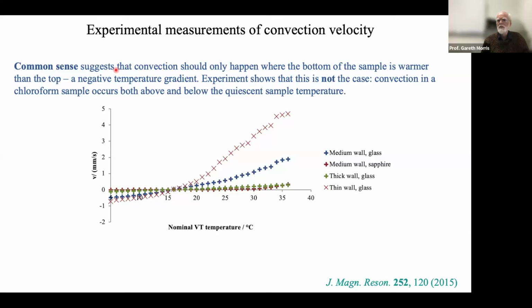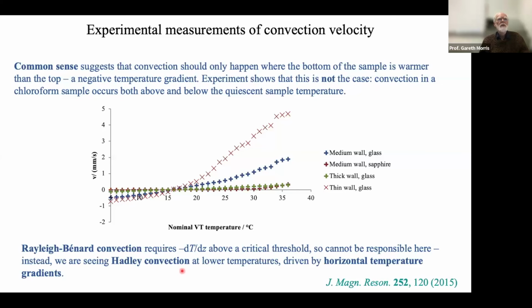In practice, if we measure the rate of convection in an NMR sample as a function of what we set the VT to, we find that, yes, there's one temperature at which there's very little convection, but stray from that either above or below, and things still convect. And the reason is that the convection is being driven not by the vertical temperature gradient here, but by a horizontal temperature gradient. Vertical convection, Rayleigh-Bénard convection, is a critical phenomenon. Unless you have a big enough gradient, it doesn't convect. Hadley convection isn't critical. It's always there to some extent.